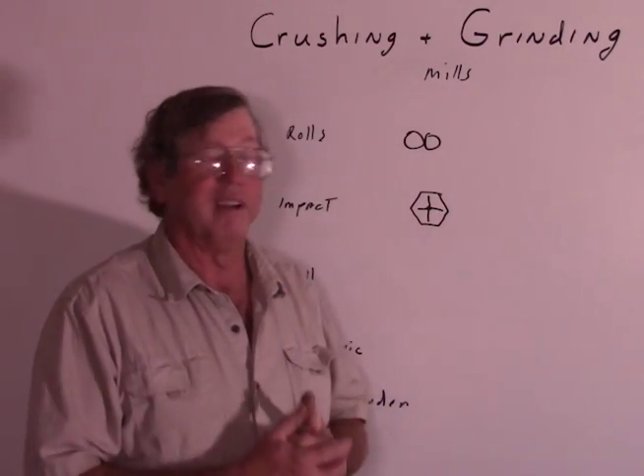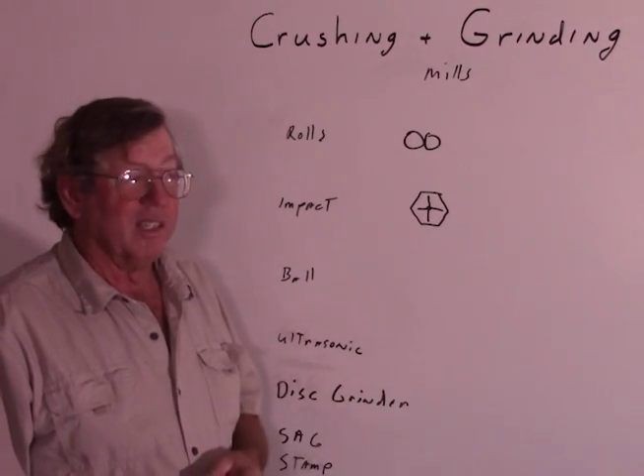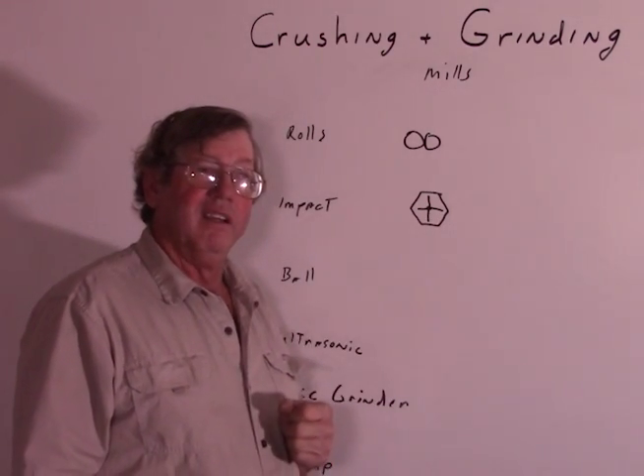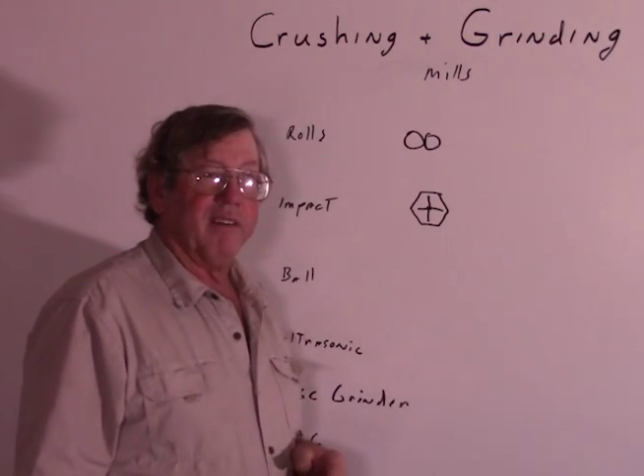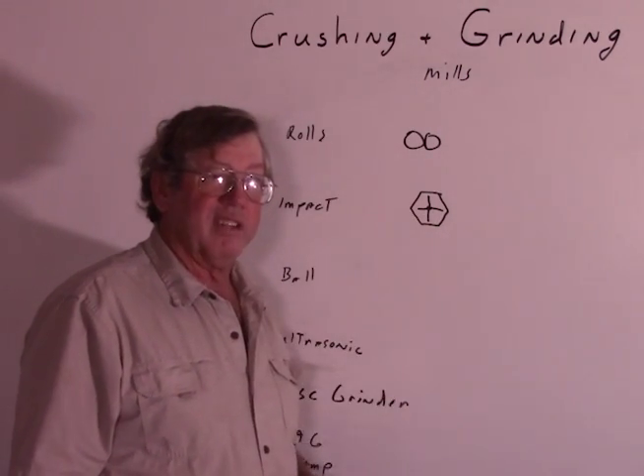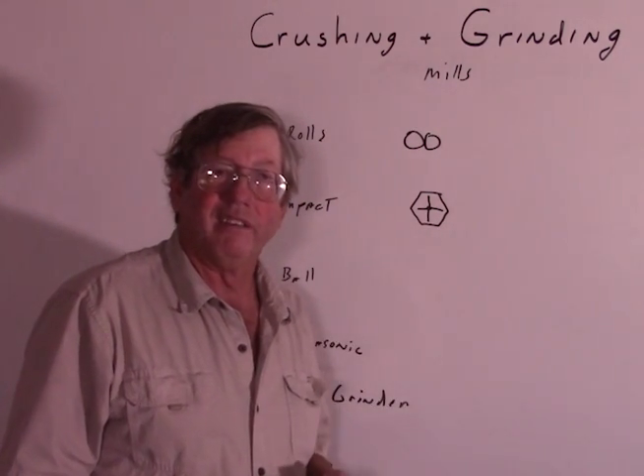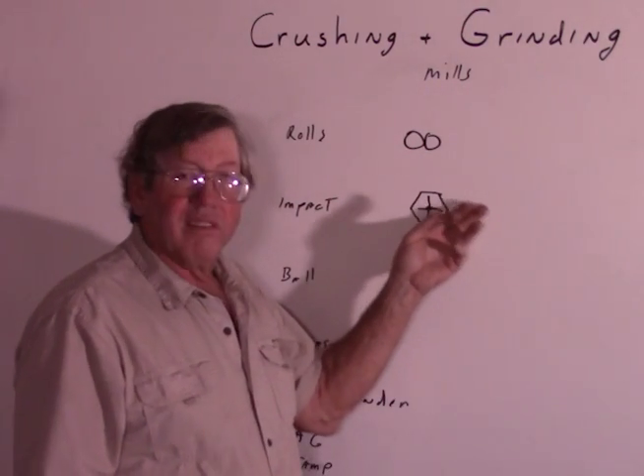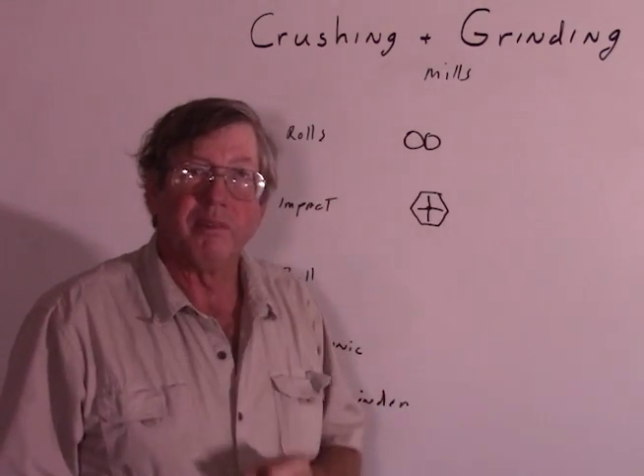An impact mill will create a lot more fines of your softer minerals than of your harder minerals. In our case with quartz and pyrites, the pyrites turn to dust while the quartz still remains chunks — bad for gravity separation, not necessarily bad for a leach. Another thing that can sometimes work well is to run through the impact mill and then screen it. If your valuable minerals are soft, they can get turned to powder while the quartz is still chunks or sand. You can screen those out and might get a 90% upgrade simply by screening. So it's worth looking into whether this process works better for your particular ore.